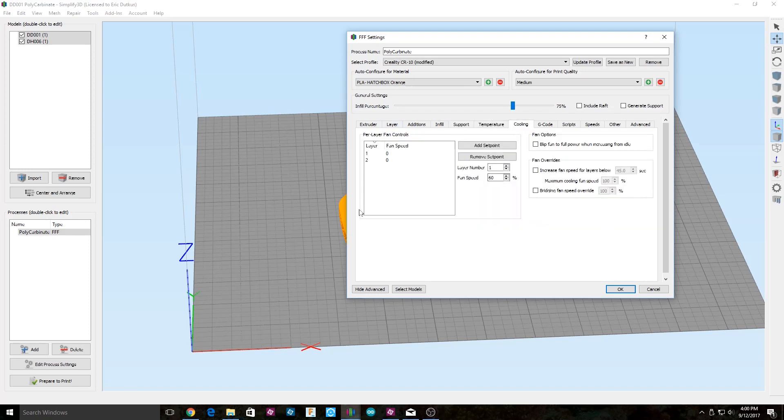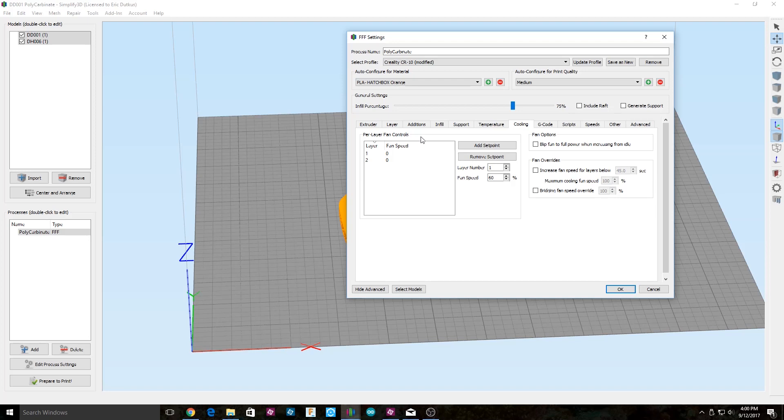Now cooling, and this is important. I tried many different prints with different variations of fan speeds, and if you have a fan on it and you have no enclosure, you're going to warp it. So make sure, if you do not have an enclosure, turn off your fans. The quality kind of goes down, but you'll still get a decent print.